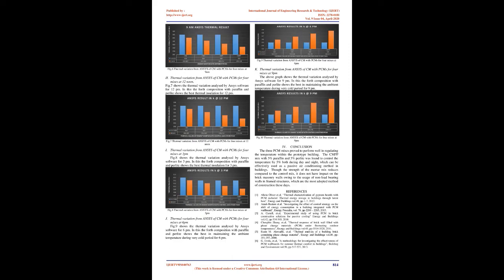The temperature variation in the 4 prototype models were studied for 30 days during morning, afternoon, and evening. The temperature readings were taken using an industrial temperature sensor for 12 hours per day. Also, to find the thermal variation in the prototype, ANSYS modeling software was used to model the thermal variation of the 4 models with the same materials and dimensions and plotted to get the 2D thermal variation of brick, as shown in Fig. 2. Fig. 2: two-dimensional pattern of wall brick done using ANSYS software.